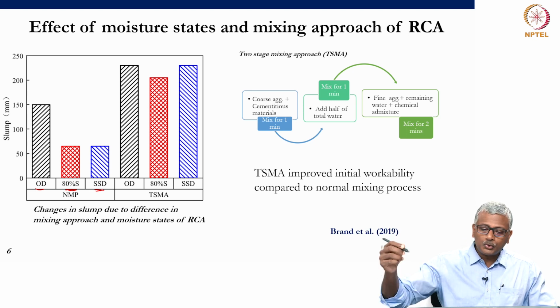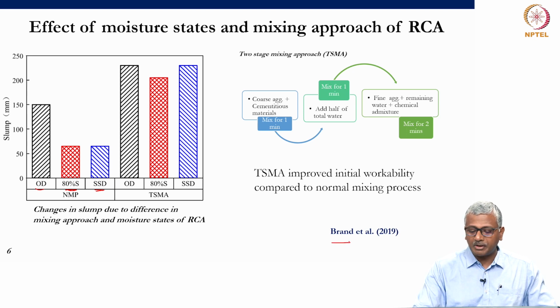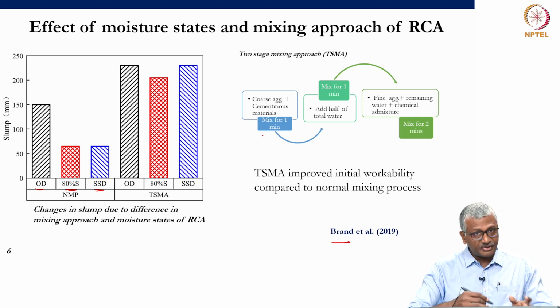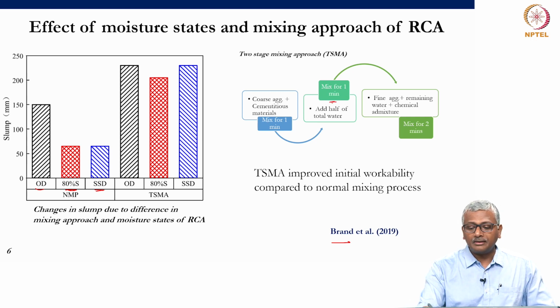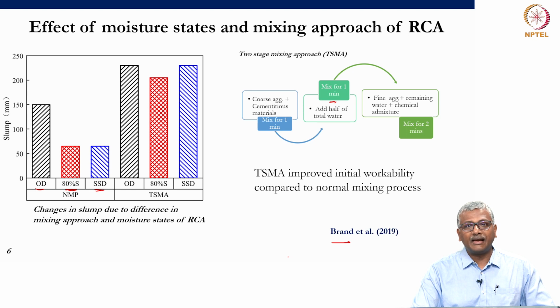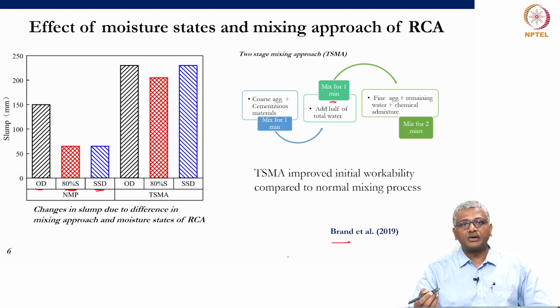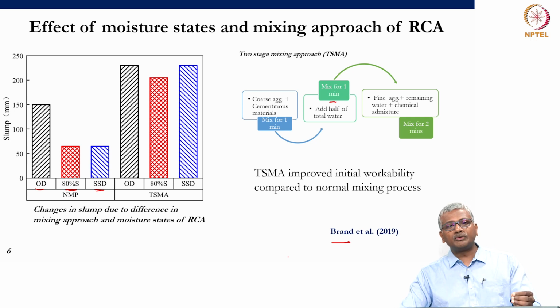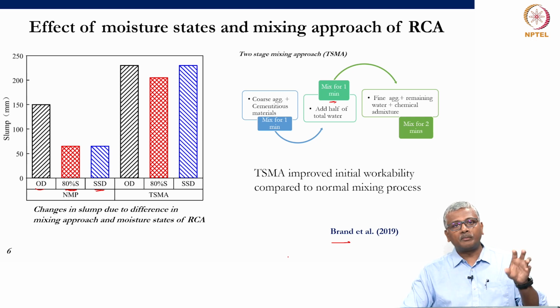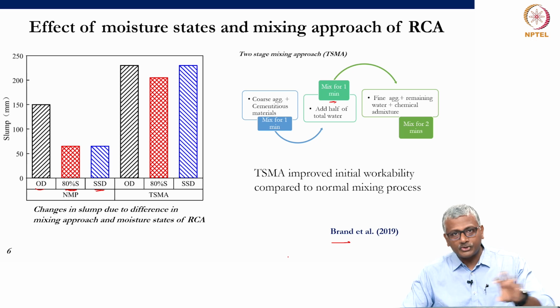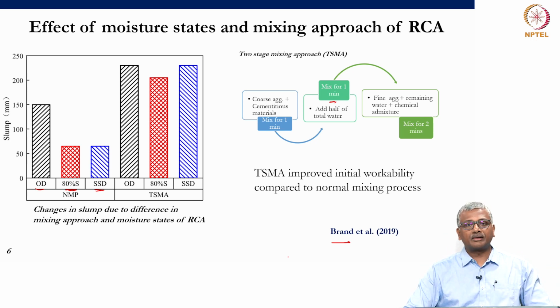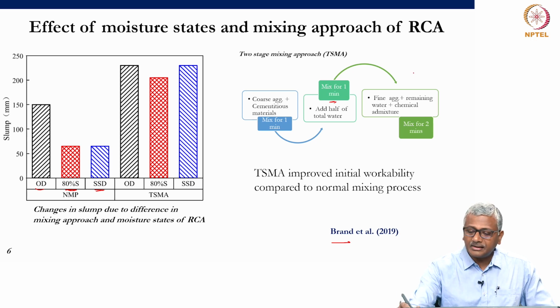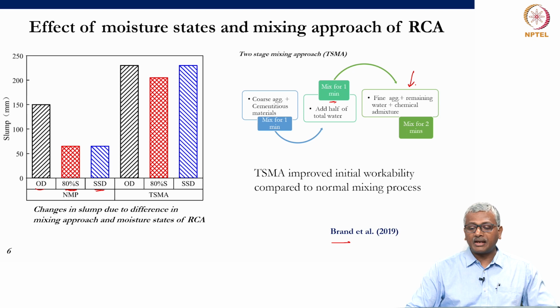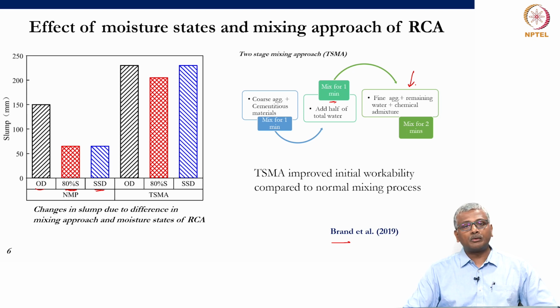But if you adopt this two-stage mixing approach, for instance, in this study by Brand et al., they showed that in the two-stage mixing approach, the coarse aggregate and cementitious materials were mixed first, okay, then half of the water was added and a further mixing for 1 minute was done. What does this do? When you add half of the water that is required to compensate for the absorption by the coarse aggregate, it first goes into the pores of the coarse aggregate. So, that means that it is completely saturating the coarse aggregate. Then you add the remaining water along with the fine aggregate and chemical admixture and further mix for 2 minutes to prepare a homogeneous blend.